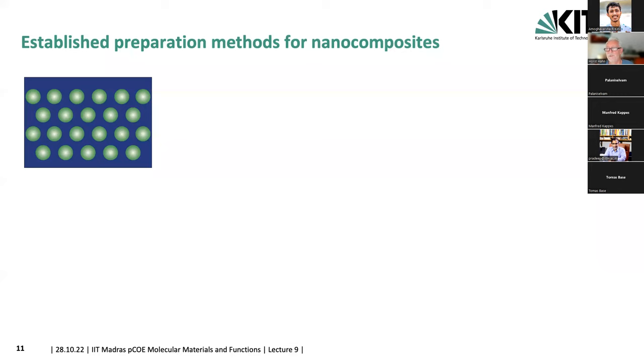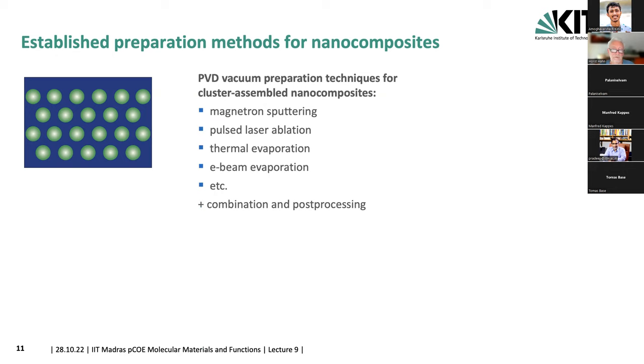If you loosen the conditions a little bit, you have a whole range of materials combinations and also of physical vapor deposition techniques to build such cluster assembled materials. If you have a binary system where there is at least a partial or complete immiscibility of the two elements, then you can just use any of the thin film techniques and do a co-deposition using magnetron sputtering, pulsed laser ablation, thermal or e-beam evaporation, etc. Then you co-deposit the two materials and they will phase separate because they don't like each other. They would rather be surrounded by their own instead of by the other element. Sometimes you have to do some post-processing in order to get such a structure, which is schematically shown over here.